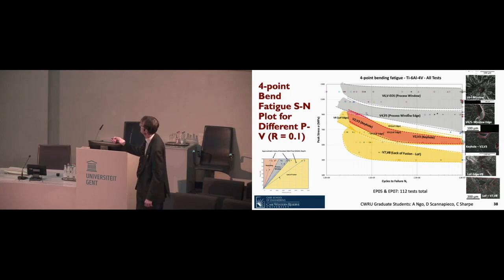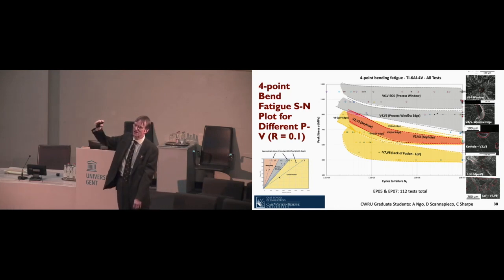So if you print over here, where you have basically Swiss cheese, I hope that was an okay thing to say here, then you get terrible results, that the alternating stress that the material can sustain are quite low, far lower than you would hope for conventional material. On the other hand, to make the contrast, if you put your printing squarely in the middle of the process window, you get the result all the way up here. And I know you can't really read these numbers, but here we're talking about alternating stresses as high as 1,200 megapascals. And that is deceptively higher than you see in ordinary fatigue testing of conventional material.